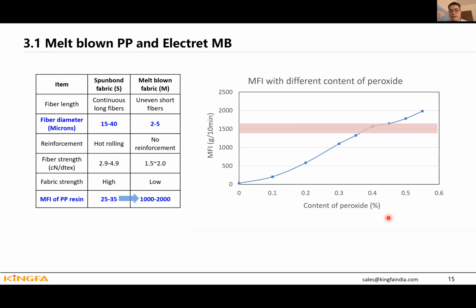And we can use peroxide. We can add some peroxide in the PP, and then we come to the extruder. Then we can get a high MFI. So we tried different dosages of this peroxide, and the MFI increased. Finally, we get 0.4% of peroxide, then we can get 1500 MFI. So this is how we make this product. They have some reaction in the extruder, then the PP molecular weight can decrease. Then we can get a higher MFI meltblown fabric.